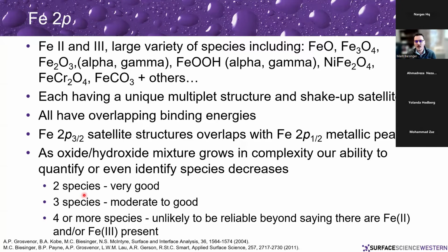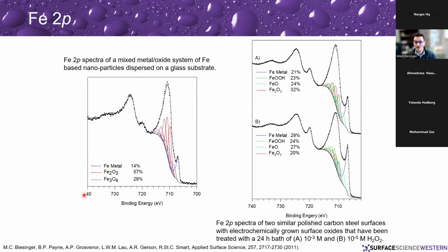So as the oxide and hydroxide mixtures grow in complexity, our ability to quantify or identify these species diminishes very quickly. 2 species, very good analysis. 3 species, moderate to good. 4 or 5 more species, and you're really starting to push the limits of what you're able to pull out of these things.